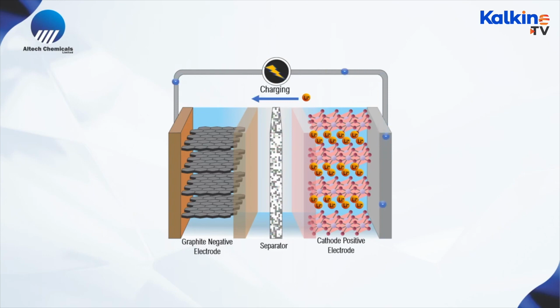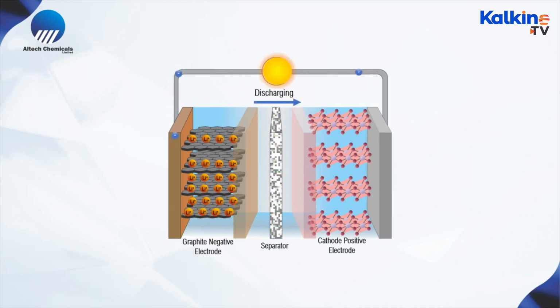It sounds very interesting. Now, your company also announced some developments on using high purity alumina as coatings on graphite anodes. Can you tell us more about this, please? Yeah, Rachel, we've developed a technology where we use our high purity alumina coatings in graphite materials. Now, as you know, graphite is an anode material in lithium ion batteries. What a lot of people don't realize is that when you first charge a lithium ion battery, the lithium ions go from the cathode to the anode. When you discharge it, the lithium ions go back the other way.